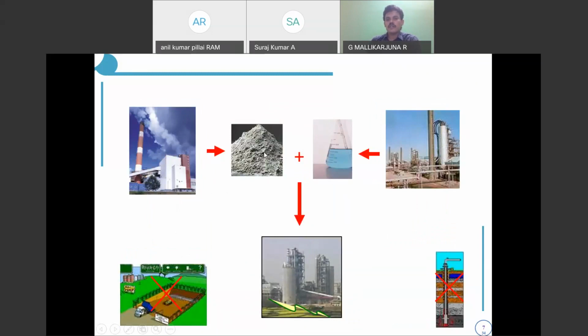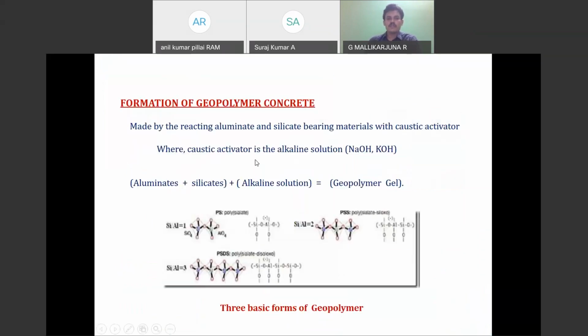So fly ash plus alkaline activator is going to produce a certain amount of strength. There are certain limitations whenever you use only the geopolymer, meaning fly ash as the source material. For the formation of the geopolymer, we have the aluminates plus silicates in the source material and the alkaline activator solution. We mix both materials and we get the geopolymer gel. That gel is produced mainly based on the silica to alumina ratio.